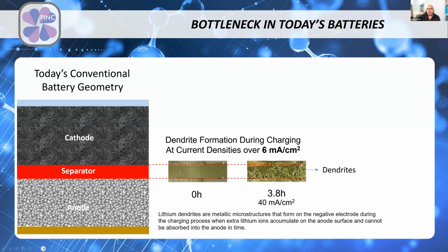Usually the magic number for current density is 6 milliamps per centimeter square. As you see, it's about the surface area that they are exposed to. It's not an exact number. It's roughly over 6 milliamps per centimeter square. So you start to see very fast dendritic formation, which is essentially lithium starting to interact with each other in a process called electroplating, and they grow these crystalline structures, which eventually short the anode and cathode.